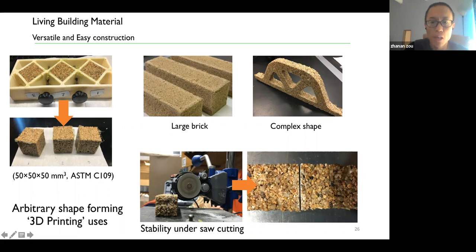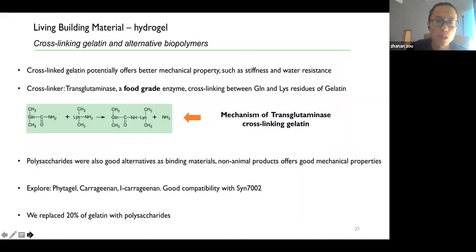So the material that we make, as you can see on the bottom pictures, has good processability, in that we can use a diamond saw to cut a nice notch, as you can see on the red bottom picture, and the bricks or the particles will not fall off. And this is one of the samples that we used for mechanical test. We also follow the ASTM C109 for all the mechanical tests, and theoretically, since it's a material that we can build up, we can use a 3D printer in the future to build various shapes. So for the next, yeah.